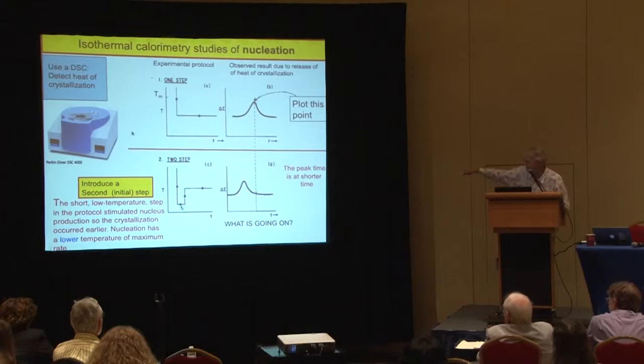So now we get a little bit more sophisticated with the protocol. Instead of doing just one step and waiting, we say, okay, if there's a nucleation TTT curve which is lying below the other one, how can we find out where it is and where its maximum is? So we invent this two-step method where we do a first short pulse drop in temperature to well below the isothermal temperature we had here, and see if it makes any difference. And sure enough, the peak now moves to a much shorter time. So we've done something to titillate the system and produce the nuclei, of course. And so by choosing the temperature to which we drop this here, we can explore the nucleation rate.